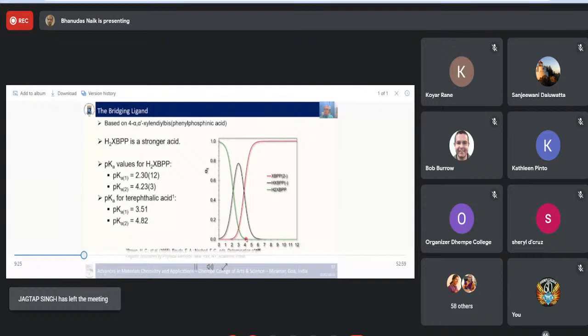And this is quite important when you do the reactions with the compound, because you can manage to dissolve the acid in a basic solution. It's a slightly basic solution, but what is first formed is this compound here. So if you don't watch out and you don't add enough base to get to pH 6, then you will have a mix between these two compounds, the monoanion and the dianion, which will give a mixture of products in the reactions afterwards.